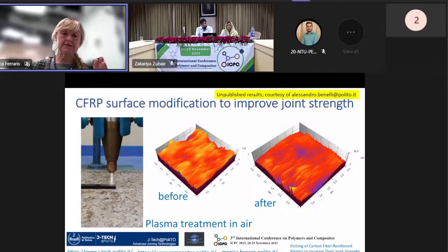So another activity we are doing in parallel is surface modification of CFRP in order to improve the joint strength. Not just acidic etching, but we try to work with plasma treatment in air right now, plus in the future with different gases. As you know, it's a way to clean the surface, not just to clean but to activate the surface and improve joint strength. We have just started this activity.